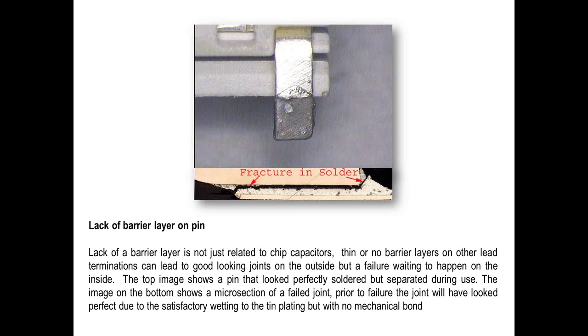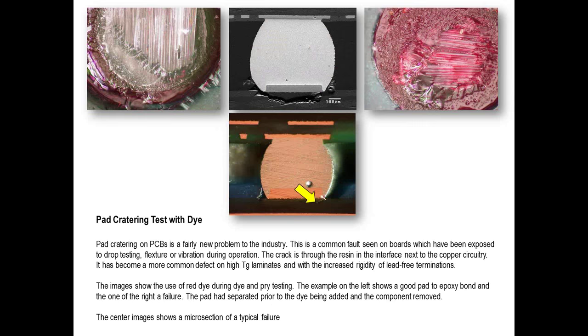So when you make a solder joint, you ideally are trying to form an intermetallic between the pin plated material and the solder. But if the solder or plating interface separates from the pin, you're going to have a very weak and unreliable joint. In this particular case, the manufacturer did not use the correct pre-plating material over the base material of the pin. That was the mistake. Typically, you'll always have a barrier layer of copper or nickel on most pin surfaces to aid solderability and wettability and to improve reliability. And in the case of some forms of metal, it's there for other reasons as well.